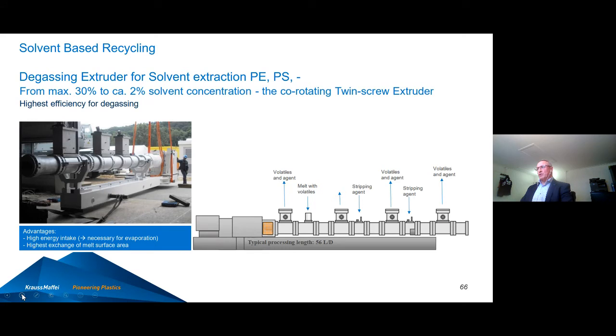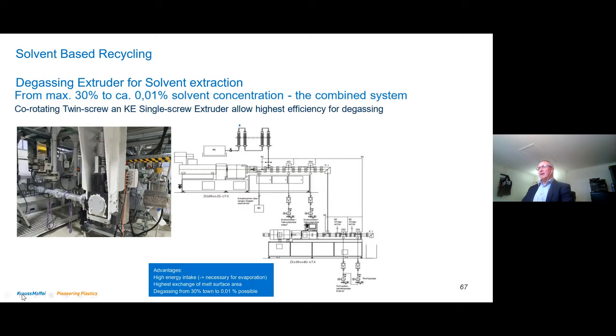This is an extruder, a twin screw extruder, having a rear vent, having 3 steps of forward venting to get as low as possible from 30% of solvent back to 2%. The next slide, please, otherwise time is running out. And this is showing that we can also come from 30% down to 0.01% by having a tandem setup, the first extruder being able to get out the flash degassing steps, and the second one, a single screw, going down to a very low residual content of solvent of 0.01%. Next slide, please.